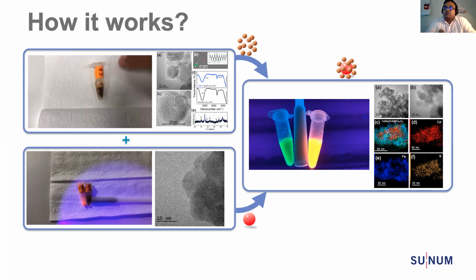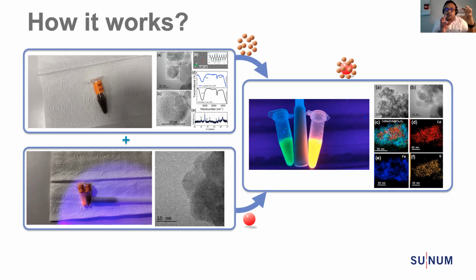We were interested in precisely controlling 10 nanometer size. As you see in the SEM and TEM image at the top here, it's roughly, not precisely, close to 10 nanometer, which is what we wanted, because we wanted to keep the dimensions of our quantum nanocrystals and the iron oxide nanoparticles identical in their size, so as to make them fluorescent, as good as quantum dots do,